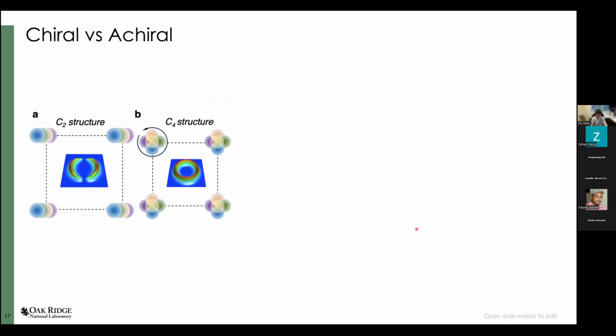Now, having the transverse Peierls transition in europium aluminum 4 established, we can ask whether the CDW is chiral or achiral. One way to distinguish it is to check the rotational symmetry in the CDW phase. If it's C2, it is very likely a C2 or nematic charge density wave. If it's C4, then there's a possibility to host a chiral CDW.